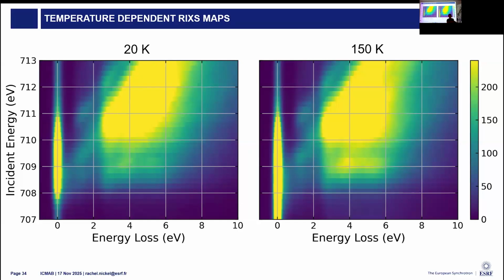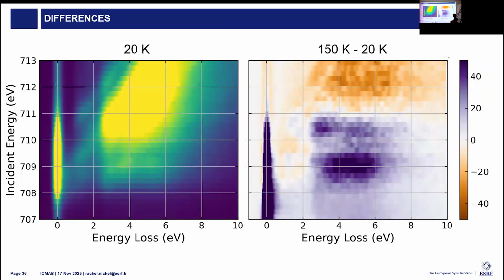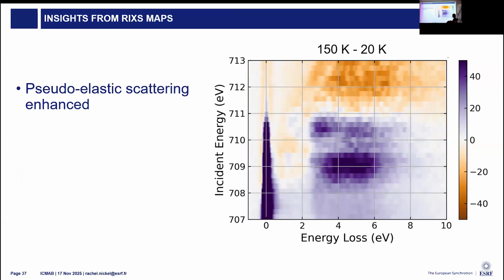So we measured at 20 Kelvin and 150 Kelvin. So we're in the incommensurate structure on the left and in the ferrimagnetic structure on the right. And there are differences. It's terrible to spot the difference, but if we subtract the 2 maps, we can see that there's enhancement in purple of some regions and a reduction in intensity of others. So working left to right, we have pseudoelastic scattering that's enhanced below the resonant energy.